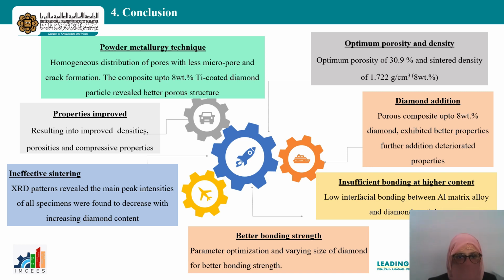Also, the XRD peaks reveal that the main peak intensities of all the samples decreased with increase in diamond content. So it reveals ineffective sintering because of the presence of low wetting between the aluminium and the diamond particles. So all this can be improved by parameter optimization, varying the diamond size, or coating the diamond.